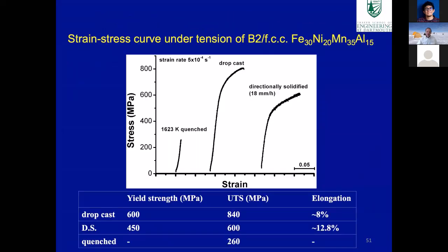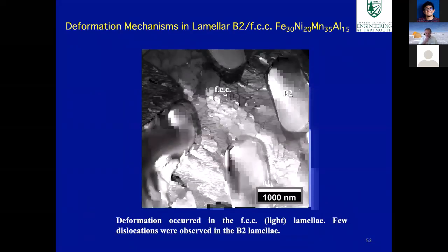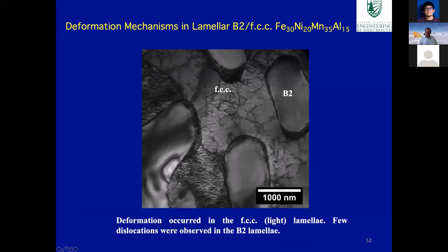We did some mechanical testing on those different microstructures, and the quenched microstructure was actually quite brittle, so we didn't manage to get any ductility at all. The slow-cooled material had a strength of about 600 MPa, and the directionally solidified about 450 megapascal. One of the interesting things when you deform this and you look at it in the TEM afterwards is that basically all the dislocation activity is in the FCC phase. And at these sort of strains to fracture, there's really little activity in the B2 phase. The reason for that is we've done nanoindentation on these two phases, and the B2 phase is actually about twice as hard as the face centered cubic phase.